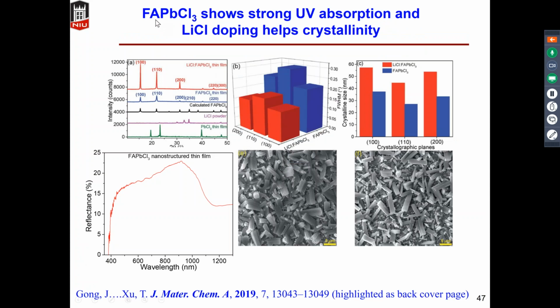So we use FAPbCl3 based perovskite nanowires as the UV absorber, because we found that they have very good absorption in the UV region, especially this deep UV region. And as you can see from this reflectance measurement of a thin film of FAPbCl3 nanoparticles, by adding lithium chloride into the precursor solution of formamidinium lead trichloride, we can actually improve the crystallinity of the resulting nanoparticles, nanowires or nanorods.